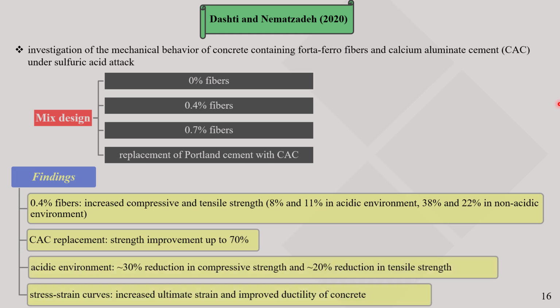The key finding was that a 0.4% fiber content could enhance compressive and tensile strength, and replacement of Portland cement with CAC increased strength by up to 70%. Overall, the acidic environment led to a reduction in compressive strength by up to 30% and tensile strength by up to 20%.